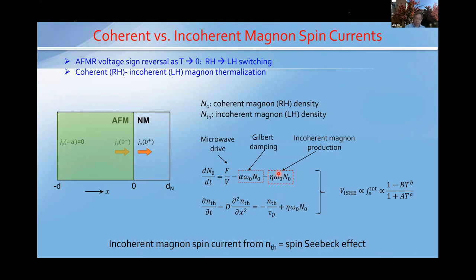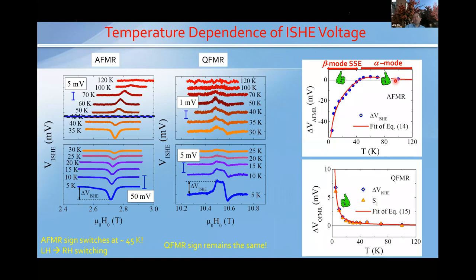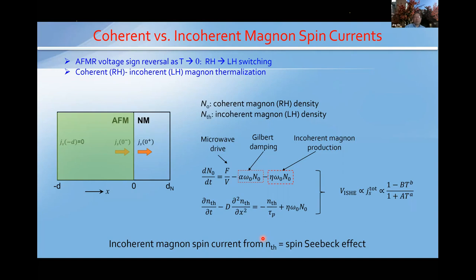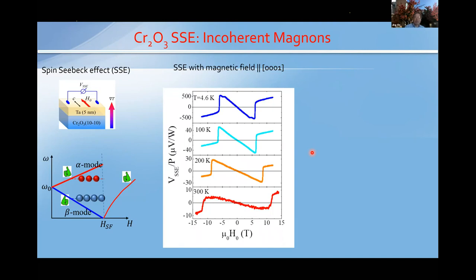For the incoherent magnon density, we have this diffusion equation in this antiferromagnetic slab. Then spin diffuses towards this interface, and is detected by the inverse spin Hall effect. So these two equations give us this inverse spin Hall expression, and the solid fit here is from this equation. So we think that incoherent magnon production is really important in chromia at low temperature. But why, not only the sign change, but the magnitude shoots up so drastically below low temperature?